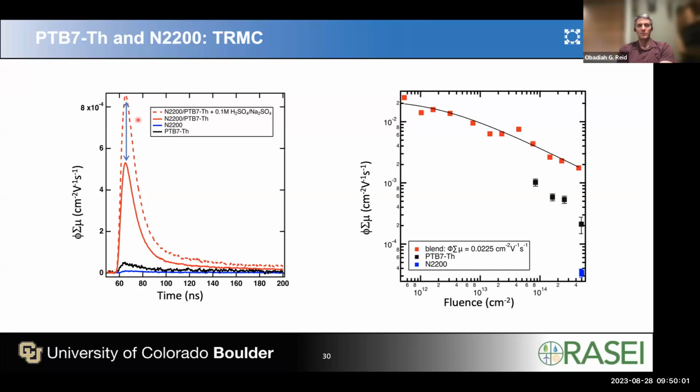And we reproduced this multiple times. But what we also reproduced was that this response decayed very quickly. So you got this initial increase in photoconductivity, and then by the time you'd finished measuring it, it would have decayed all the way back to essentially where it started. And so that convinced us that we really needed to start doing these measurements in situ, not ex situ.